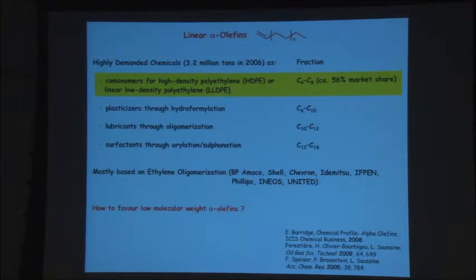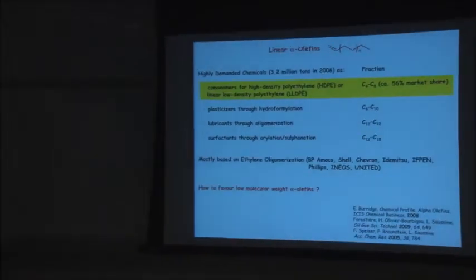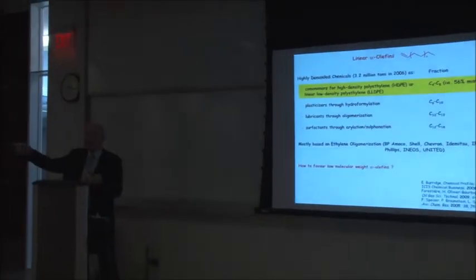I don't have the time to go into the details of the growing mechanism, how you go from C2 ethylene to C4, C6, C8, etc. But it's a kind of stepwise growth. Each time you grow the chain, you have a mechanism in organometallic chemistry called beta hydride elimination, which produces the product and regenerates the catalyst, and you can go on for the next cycle.